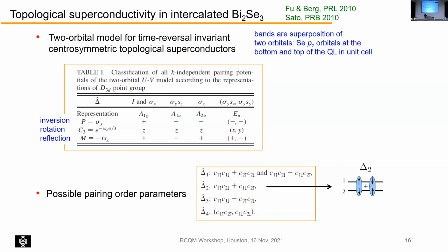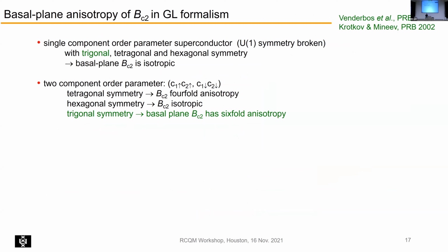Now, if you then continue and do Ginzburg-Landau theory to explain the upper critical field, you cannot get this result of this anisotropy by using a single component order parameter. So you need 2 components. And so you need this particular E_u or E_2u order parameter. And that's an order parameter that also has been proposed for uranium platinum 3, for instance. Okay, so then the Ginzburg-Landau theory that's worked out by Venderbos and colleagues. Actually, it was also done by Krotkov and Mineev in the context of uranium platinum 3. And then the statement there is, if you have a single component order parameter, and for all the different symmetries, whether it's trigonal, tetragonal, or hexagonal, the basal plane should be isotropic. So no anisotropy. That was also found for uranium platinum 3, which is a hexagonal system.